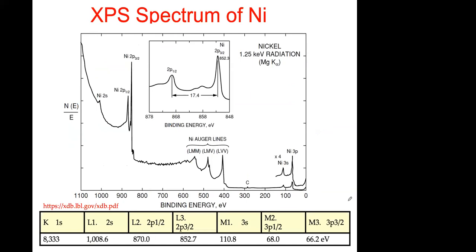The other important thing, this is another example of nickel. Again, it's the same thing. Here you have the nickel L1 at 1,000, the 2S, and here is the 2S. You have the 870 and 852 for the 2P levels, and they're basically here between 850 and 900. And then you have closer to the valence band, the 3S at 110, it's here, and 68 and 66 for M2 and M3, they are together here, you cannot resolve them. And here is zero, this is the Fermi level.